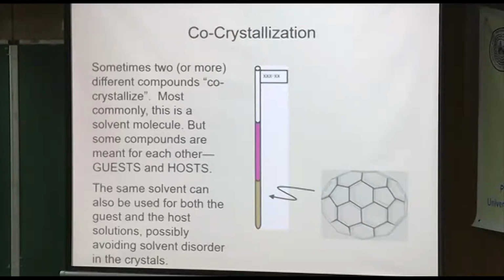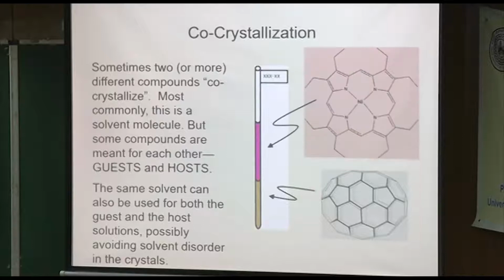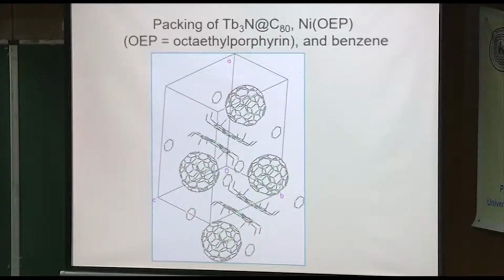So for example, fullerene, a carbon cage, in this case on the bottom, dissolved in possibly toluene. On the top, nickel octaethyl porphyrin, also dissolved in toluene, layered on the top. Okay, wait a week or two or three, and eventually some crystals grow, black, shiny crystals. And here's an example of a crystal structure.